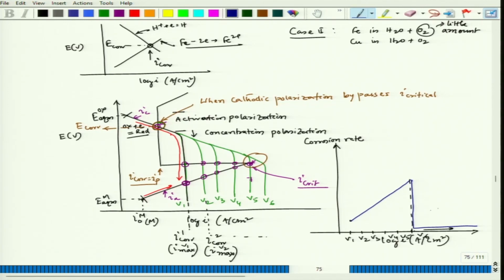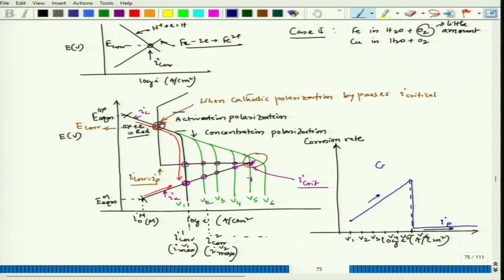Okay. So, now you see initially corrosion rate increases and this corresponds to I p, and here with the velocity the material is actually maintaining active dissolution, and once that V 5, which is the critical velocity just touching the I critical, once we cross that velocity from V 5 onwards, we get a strong passivity and the material would maintain a low corrosion rate, or we can say that we can achieve very good corrosion protection. And this particular thing we call case 3.